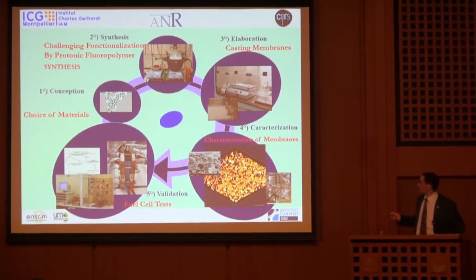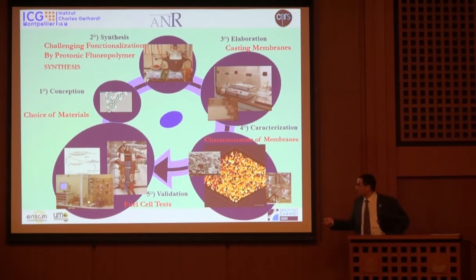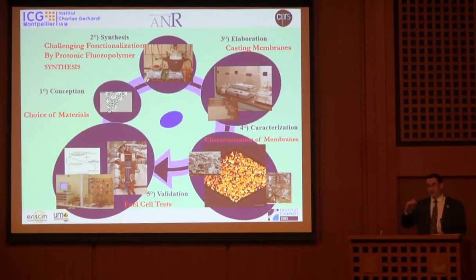And then to characterize the membrane by electron microscopy or confocal microscopy, and then to prepare the MEA and, thanks to electrochemists, to investigate the polarization curve. So here you increase the current and you see what's going on for the voltage, and you try to get it as parallel as possible. Of course, you have some loss arising from the electrodes here and here, and also from the resistance of the membrane. So these kinds of curves, called polarization curves, are very important because you try not to lose voltage and to maintain the voltage.